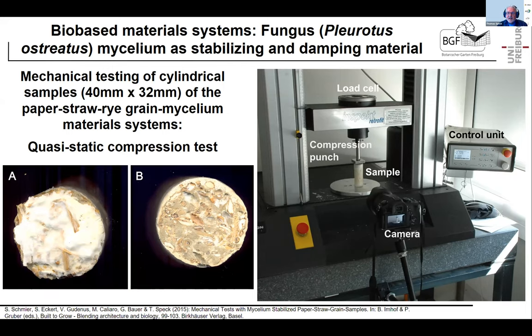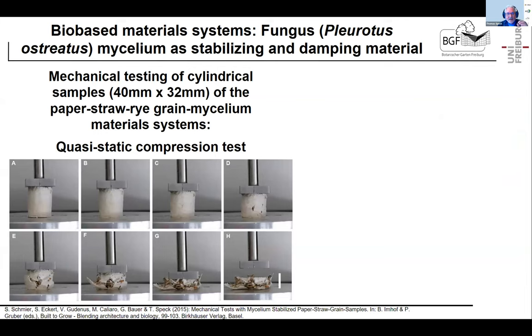Before testing, and I think this is important, we killed the fungus by putting it into an oven at around 80 to 120 degrees so that the fungus is dead. And then we tested it in a dry condition, and we did first quasi-static compression tests. You see the setup: a load cell, compression punch, sample camera, and control unit, just a simple Instron or whatever you use for that. And it's interesting, you see here single pictures of the compression. And you see at the end, it fails.